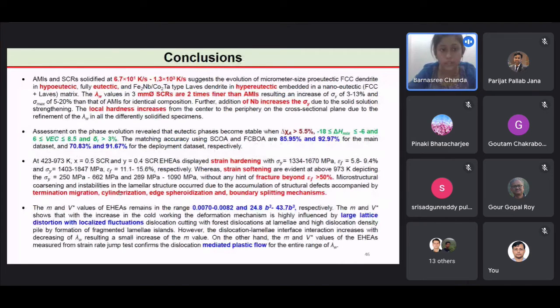So from the other chapter, we have summarized that we have successfully prepared two new series of eutectic high-entropy alloys, and with the addition of niobium and tantalum, the microstructure varies from hypoeutectic to eutectic and hypereutectic. Also, the average eutectic lamellae thickness is lowest in case of suction casted rod, which results in the increase in the yield strength. The local hardness increases from the center to the periphery on the cross-sectional plane, which is due to the refinement of the average eutectic lamellae thickness. We have assessed and predicted the phases based on various thermo-physical and electronic parameters, and we see that the phases become stable when the electronegativity parameter is 5.5% and the mixing enthalpy is in the range of -18 to -6.